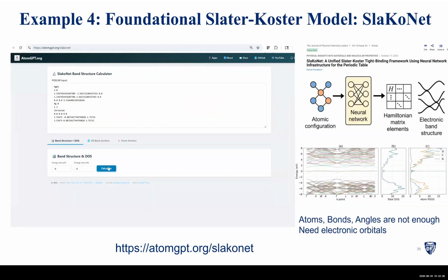Now, this is great, but the ALIGNN model did not consider electronic orbitals, which are important for predicting band structure. This is where we propose this idea called SlakoNet, the Slater-Koster tight-binding neural network, where you take an atomic structure, and instead of representing it with bonds and angles, you represent it with the spdf orbitals: s, px, py, pz, and so on. Now, for each atom and its corresponding bond distance, you get a Hamiltonian matrix. Those Hamiltonian matrices for each k-point, diagonalized, give you the band structure. Now, similarly, if you have an atomic structure, this magnesium boride, and run it on the SlakoNet app, it will give you band structure, Fermi surfaces.